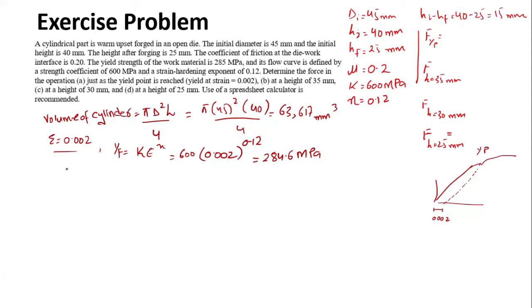Now we know that the force for forging is equal to Kf Yf into the cross sectional area. So we know the Yf. Now we have to find out the Kf and the area. We have the volume, and we have to find out the height because we have some amount of strain here, so obviously it means there's a slight reduction in the height. Our initial height, as the problem suggests, is 40 millimeter.